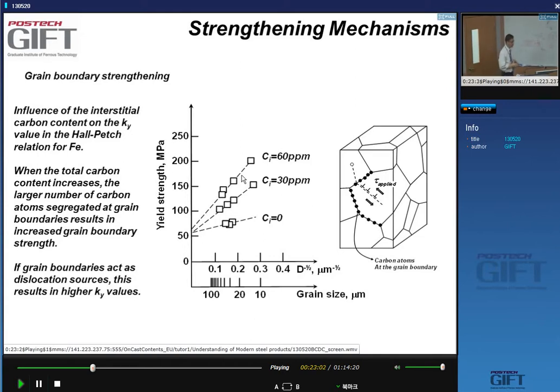One of the ways in which people have tried to explain this is that the effect of the grain strengthening is due to grain boundary properties, and in particular grain boundaries emitting dislocations, rather than the bulk grains creating dislocation loops. The idea is that as you add carbon, the carbon goes to the grain boundaries and strengthens them, making it more difficult for grain boundaries to emit dislocations. That's where the actual strengthening comes from. Theories have been developed on this basis, and they also give a 1 over square root d proportionality. So that makes it kind of difficult to check which theory is actually correct.